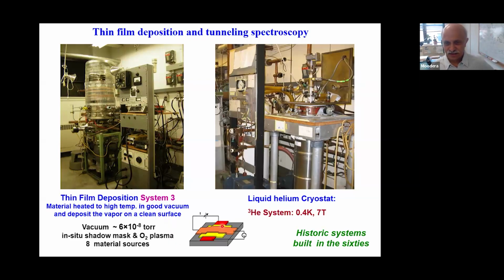They made junctions of this kind. They used, again, a home-built system, which can go down to 0.4 Kelvin, which is 400 millikelvin, and you can apply a large magnetic field to study the spin polarized tunneling spectroscopy. So what I want to show you here is that these two pieces of equipment were essentially built in the 1960s. They both are still operating.